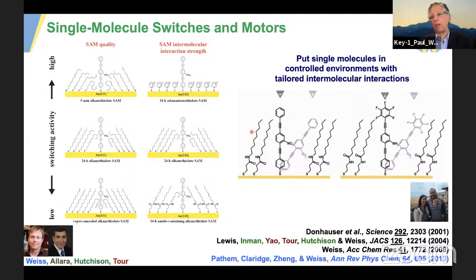Okay, and so where we took that was we went to molecules that had been discovered to be conductance switches in groups of 10,000 stuck in pores in silicon nitride membranes by the late Mark Reed. And actually, Taki Lee was a postdoc in the group at that time. And we were asked the question, could single molecules switch, which using those isolation tricks we were able to show. And then we asked the question how they switched, and we worked out the mechanism that it was a change in hybridization when the molecules tilted over, which we could control with electric field.